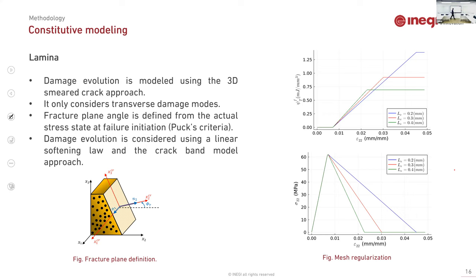All of this is also implemented, and since it is a continuous damage model, it needs to include also a mesh regularization strategy to avoid the mesh size dependence that is internally implemented. This mesh regularization is performed using the crack band approach, that is a common approximation using finite elements. This is used to guarantee that the fracture toughness translated to the volumetric fracture energy is always kept constant. So if I change the element size, we need to adjust the stress strain curves always to guarantee that the fracture toughness is kept constant, okay? To maintain the model consistency.